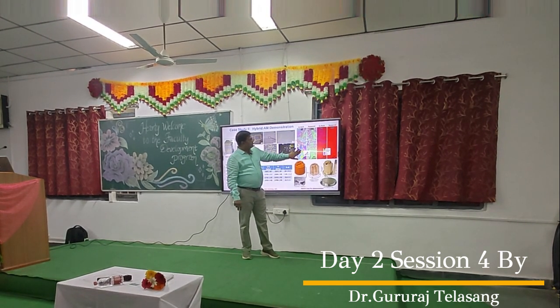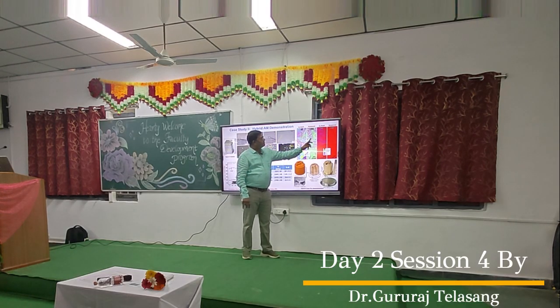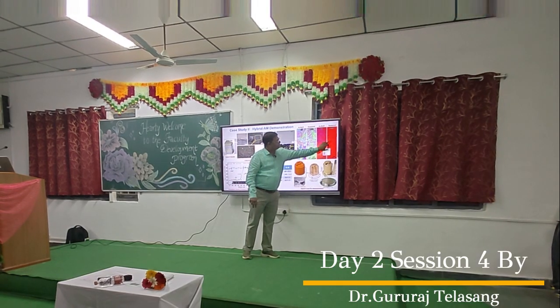This is a conventional microstructure. This is an EBSD graph. Okay, conventional microstructure. Can you see big grains? This is soft anneal. This is additive manufacturing. Can you see fine grains? When I do heat treatment, this becomes coarser, this becomes finer. Right? This is a conventional microstructure. This is the AM microstructure, which has become like this. Now, can you see the difference between them? Not much.